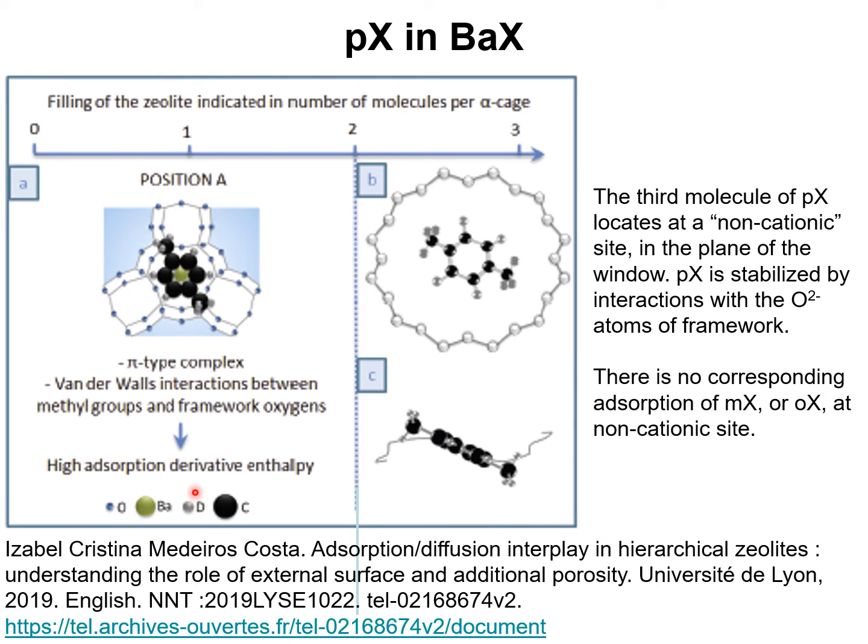In contrast to metaxylene, the placement of the third molecule of paraxylene within BaX is not energy demanding because the longer paraxylene molecule can be located in the plane of the window and is stabilized by interactions with the oxygen atoms of the framework.